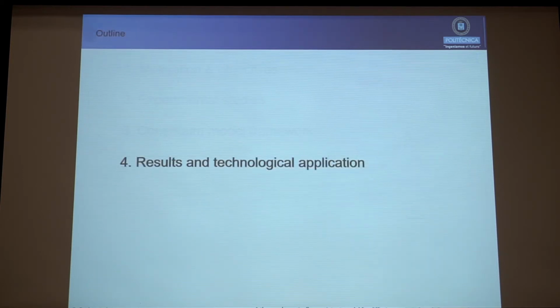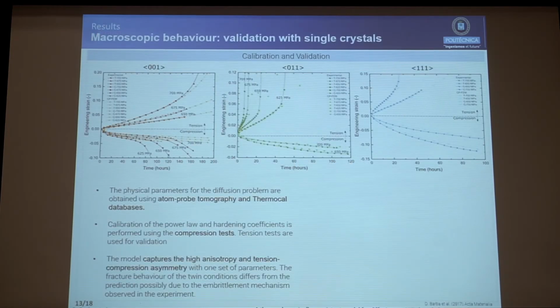And I'm going to present now some of the results related with all this continuum framework. So this is the creep test that I presented at the beginning. We have used the compression part for calibration of the mechanical constants, and the tension part for validation. So we got good agreement between the creep curves. The only part that is getting away from the experiment is this last part in 011 and 001 in compression.